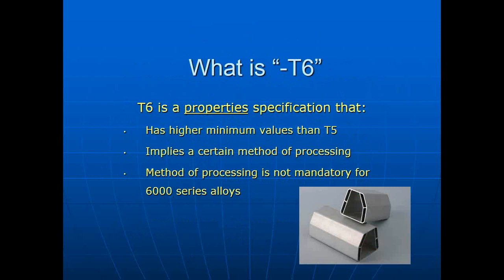And in fact, because of all the savings in labor and handling, the vast majority of 6000, essentially all of them, when you purchase a 6000 series alloy in T6, will have been through a press quench process. So it's implied solution heat treat, but really it comes back to a property specification. Are you making tensile? Are you making hardness? And so on.